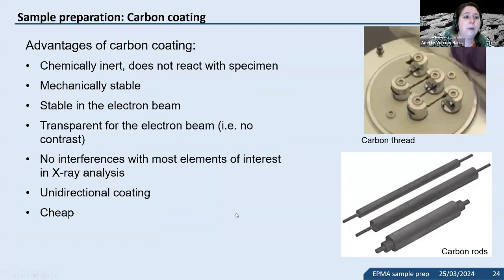Usually we like carbon coating the most for quantitative analysis. It has a lot of advantages. It's chemically inert, doesn't react with the specimen, which sometimes can be otherwise a problem with metallic coatings. It's mechanically stable, so it usually lasts quite a long time, even if you transport it around. It's stable in the electron beam. You don't have a lot of contrast, and most importantly, unless you want to analyze carbon itself, there are no interferences with other elements compared to a gold metal coating or something.